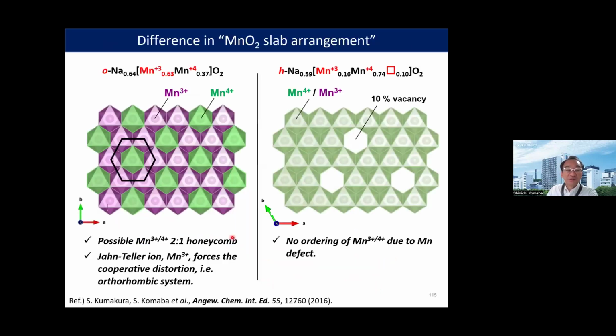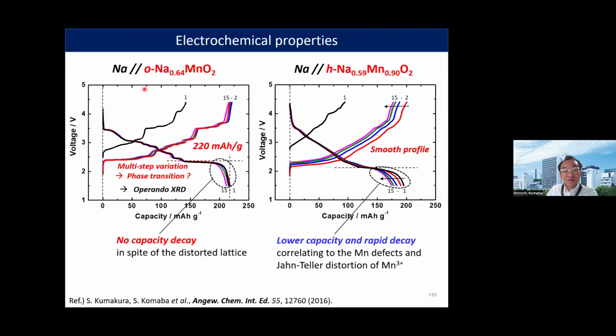So how about the crystal structure here? Because of the 10% vacancy, there is no long-range ordering. But in the case of no defects on the manganese site, manganese 3 plus and 4 plus long-range ordering, like a honeycomb structure, stabilizes this crystal structure. Then this orthorhombic distorted Jahn-Teller cooperation effect also stabilizes the electrochemical reaction during more than 10 cycles. The higher capacity can be maintained. On the other hand, in the case of the defective hexagonal phase, capacity decreases and is also limited compared to the orthorhombic phase.